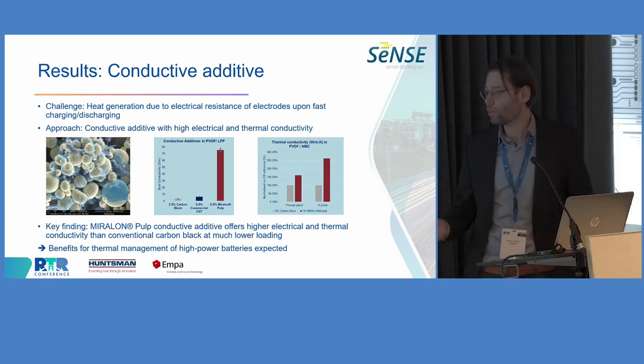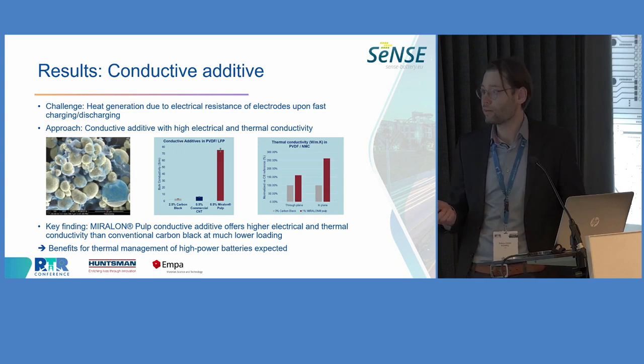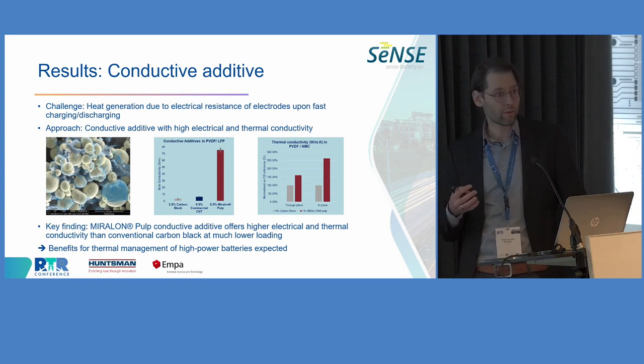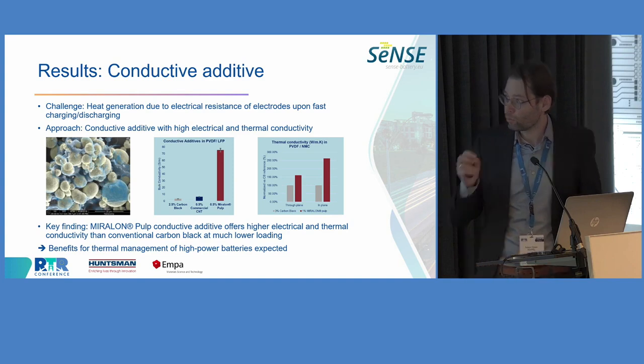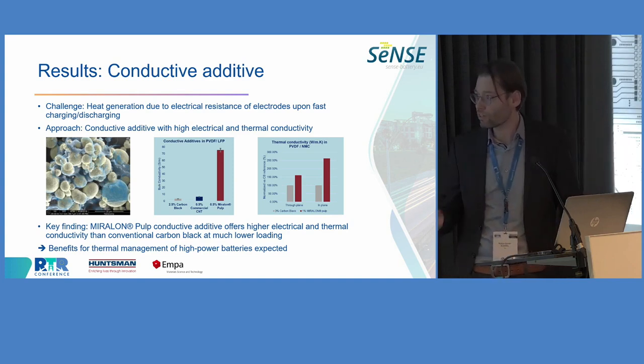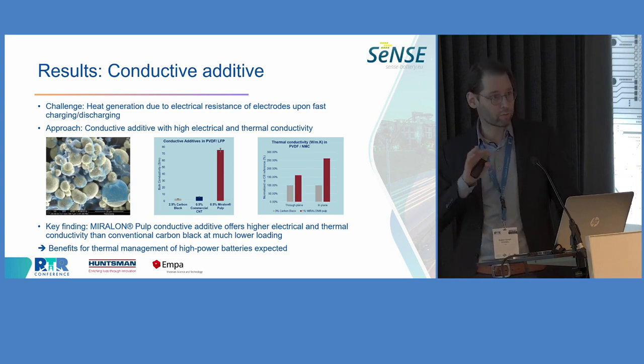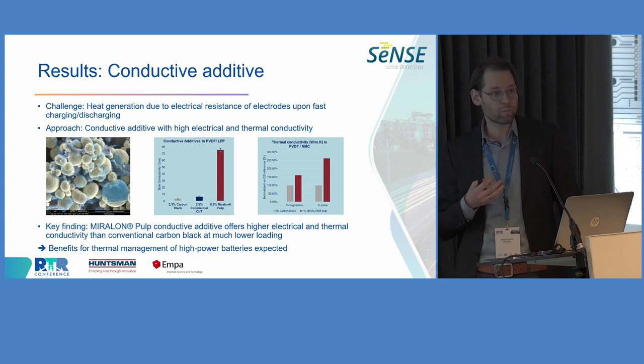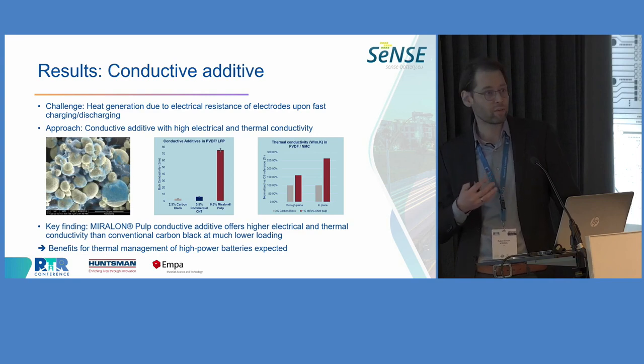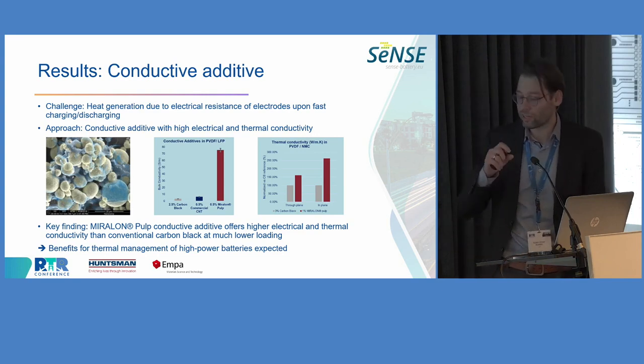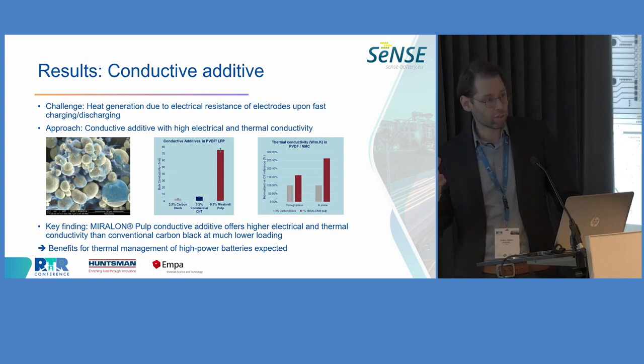Here we are working with the company Huntsman, which has a very nice material called MIRALON® Pulp, an alternative conductive additive for electrodes. When we add this additive in rather low quantities to the electrodes, around 0.5 to 1% of this material, we can significantly improve the electrical as well as thermal conductivity of the electrodes. This has a dual benefit: we are generating less heat because the ohmic resistance of the electrodes is lower, so if we fast charge or discharge the cell, we generate less heat. At the same time, it becomes easier to dissipate the heat using this material.